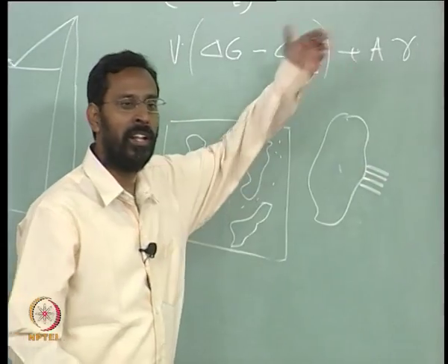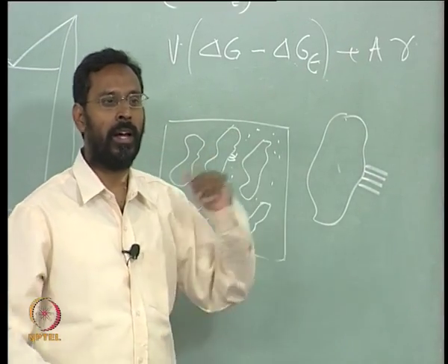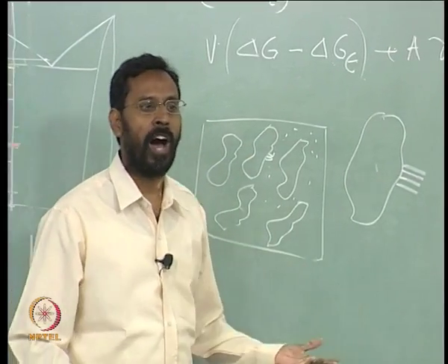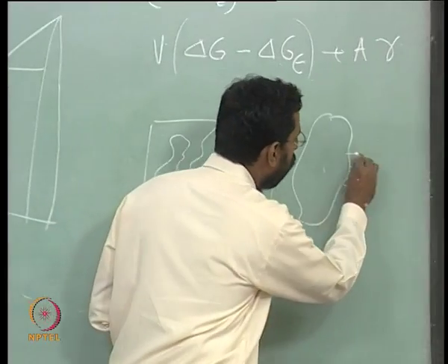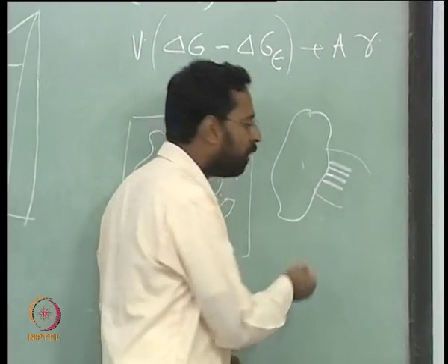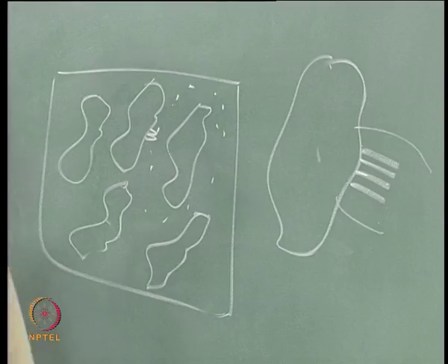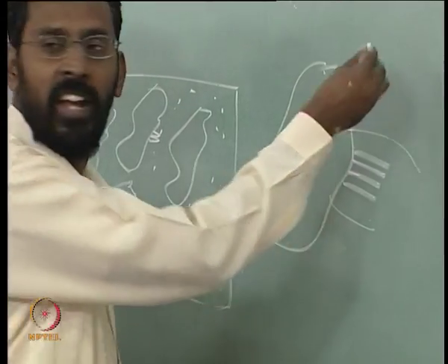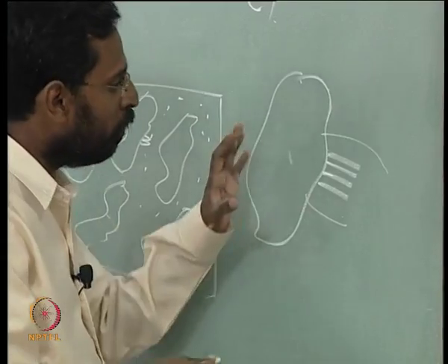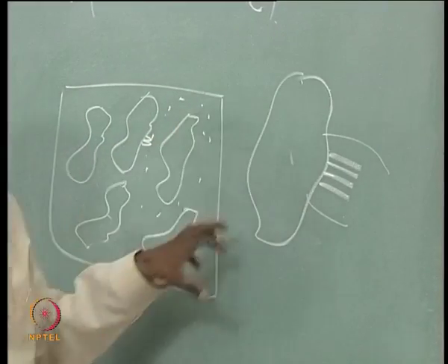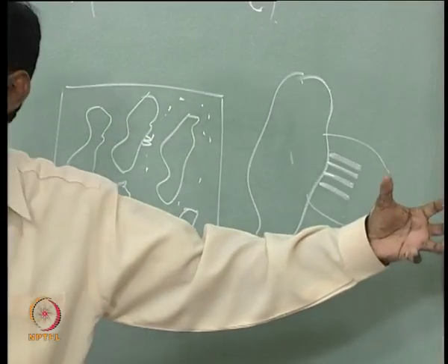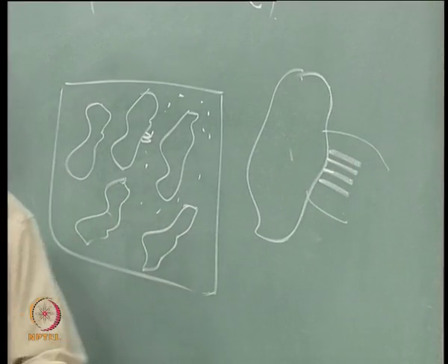Once the theta comes, the region next to it again becomes poorer in copper, so alpha comes out. So that is how a small colony forms, and that colony starts growing, and there will be another colony somewhere else, another nucleation event. So you see the whole nucleation is actually on the alpha and then grows into the liquid. This is how it happens.